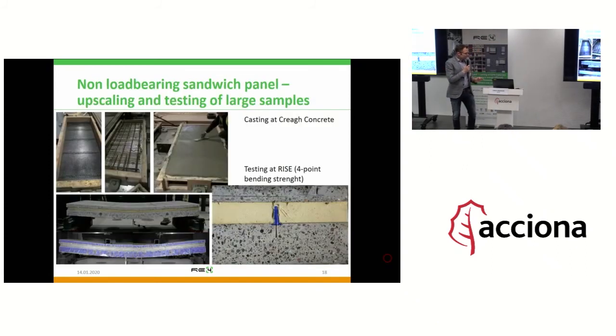So some images here: in the upper left, you see the outer layer being cast, you see the mold, and you see the carbon fiber textile. And it's cast with high performance concrete, and then you have insulation and steel reinforcement for the inner layer in the second image, and in the final image you have the casting.